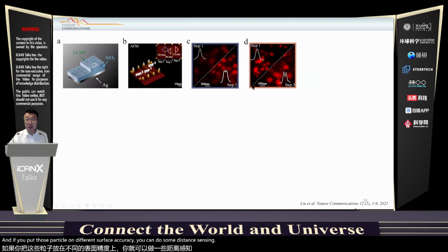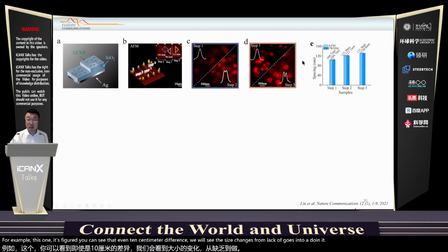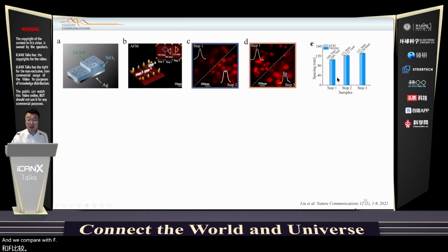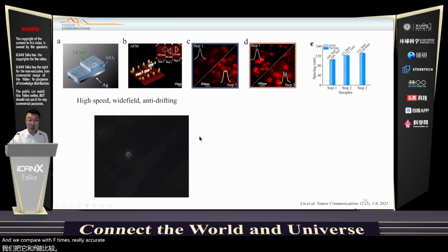For example, in this figure D, you can see that even with a 10 nanometer difference, the pattern changes from a Gaussian to a donut. And we compared with AFM, and it's really accurate. So we can do this tracking.